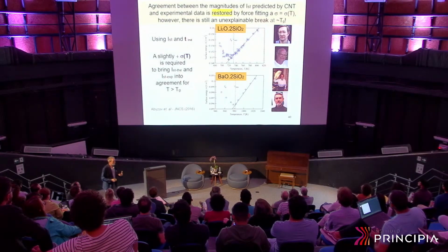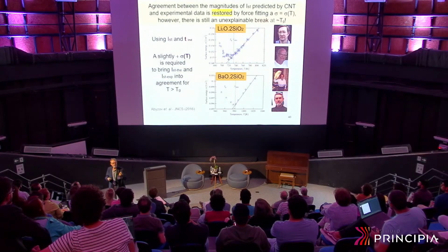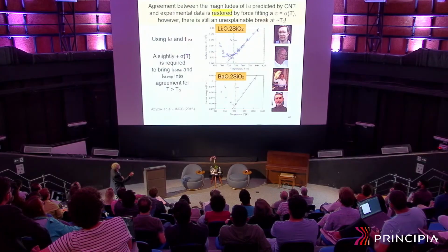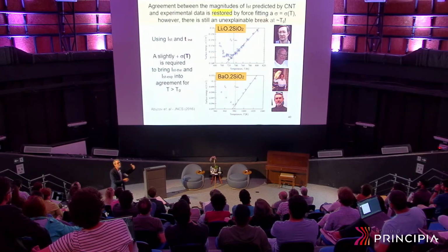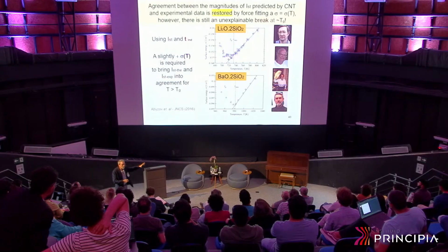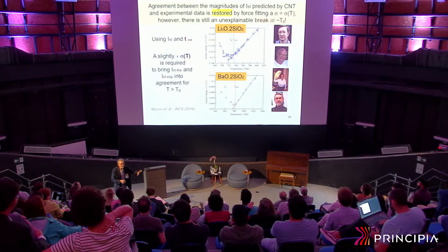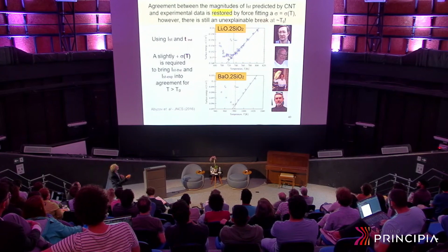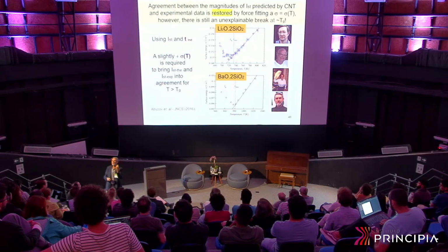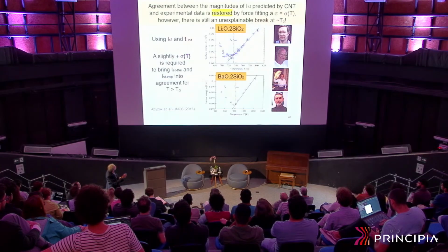Now, how can you bring back theory and experiments into agreement? You can force fit each data point. You can force fit what's the interfacial energy to bring back agreement? So by force fitting, we get this curve here. Forget what happens below TG. It's much more complicated below TG, but for the time being, forget that. I do not have time to dwell on these complications, but you get a nice straight line showing that interfacial energy is not constant. In the previous test, the interfacial energy was taken as a constant. It varies a little bit with temperature, say from 0.15 to 0.16 joules per square meter. This is joules per square meter.